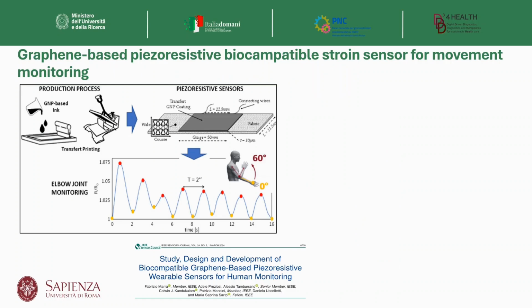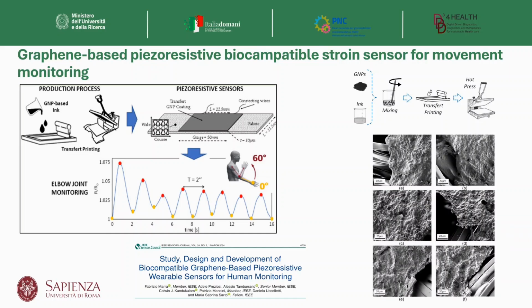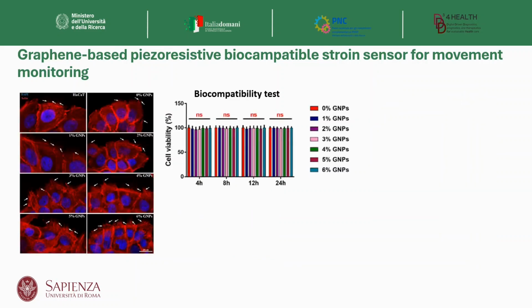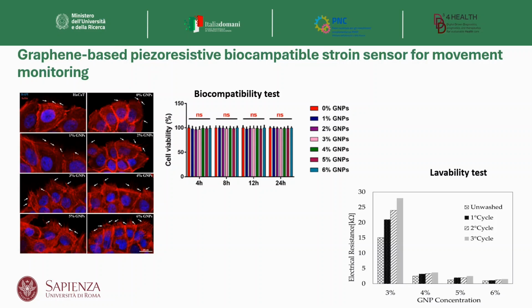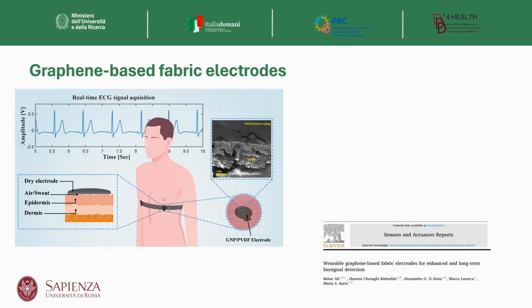This is another type of sensor, similar technology, but in this case we use a transfer printing technique in order to print the sensor on the textile. And this is the detail of the material integration with the textile. And this is an example of biocompatibility studies that we perform. You see here the live microscopy of the cells, and you see the cell viability, which is not affected for different percentages of graphene filling the polymer. And of course, another important aspect is washability. That is, the sensor response doesn't change when you wash your textile.